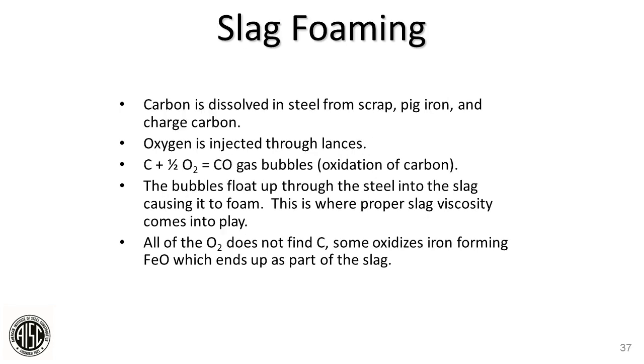So slag foaming, how is it done? The carbon is dissolved from steel, scrap, pig iron, and other charged carbon. Oxygen is injected through the lances on the side of the furnace. So basically you're making a carbonated slag, for lack of a better term. So CO, CO2, it fluffs up the slag. We have to maintain the right chemistry to get the right viscosity so it foams up. And not all the oxygen finds the carbon. Some of it oxidizes iron, which makes FeO, which ends up being yield loss to the steel processor. That's a loss of the product for us. Next slide, please.